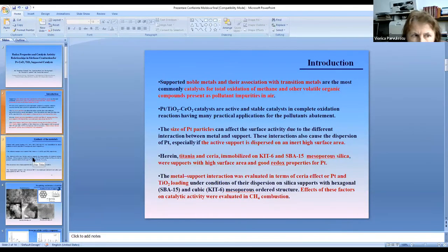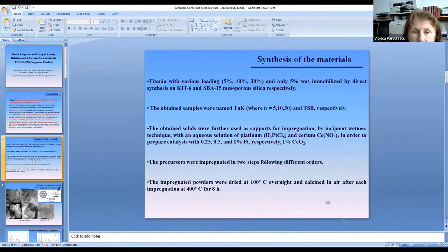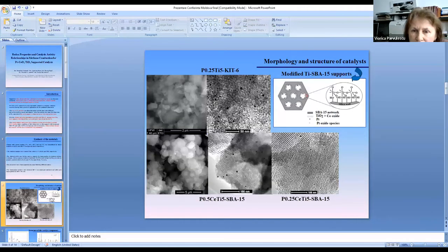In the first stage, KIT6 with 5, 10, and 30 percent titania, and SBA15 with 5% of titania were obtained by direct synthesis. The obtained solids were used after for immobilization in two steps of different precursors for platinum and ceria, following different orders. So, the obtained materials